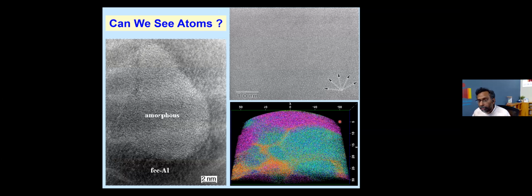It's also possible to see atoms in almost every material. For example, what you see on the left side, you see certain white dots which are arranged in some kind of lines. These are what we call atomic planes inside a material. And there is a small region where there are dots, but these dots are not arranged in any specific manner. So this is what we call an amorphous material, where there is no periodicity and complete randomness.